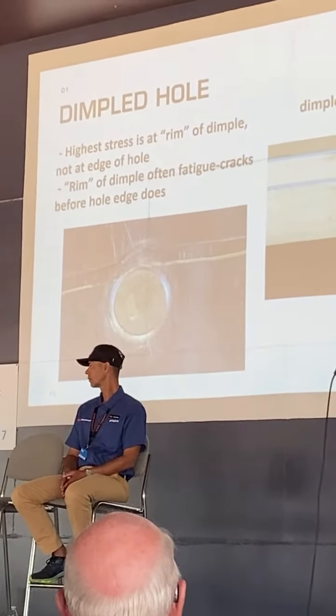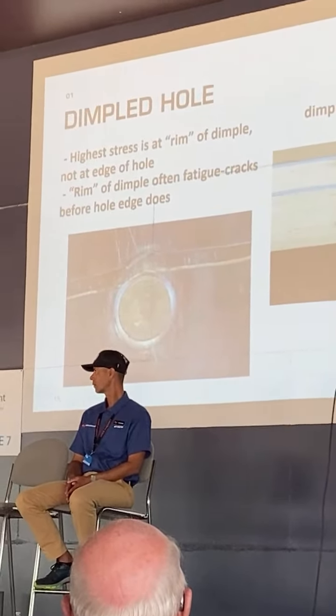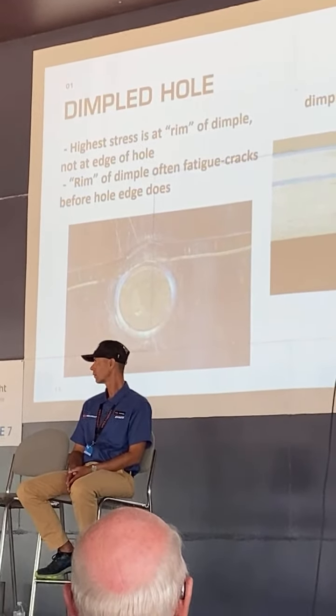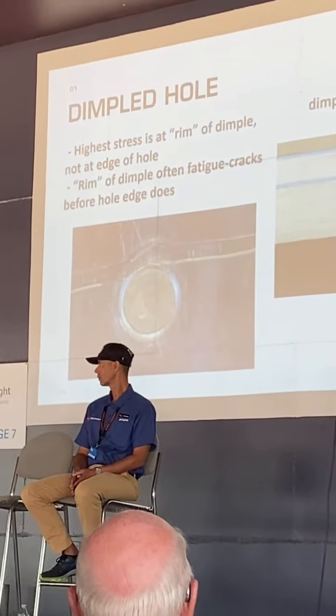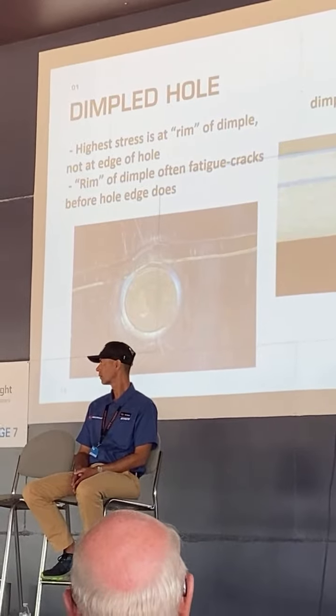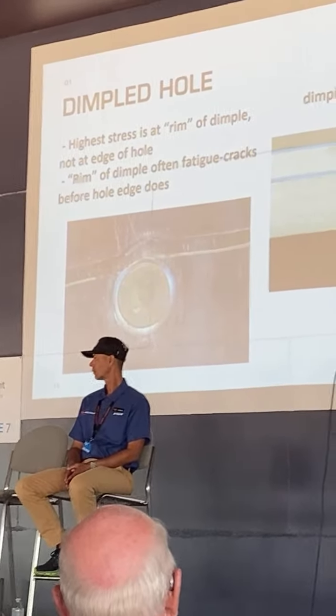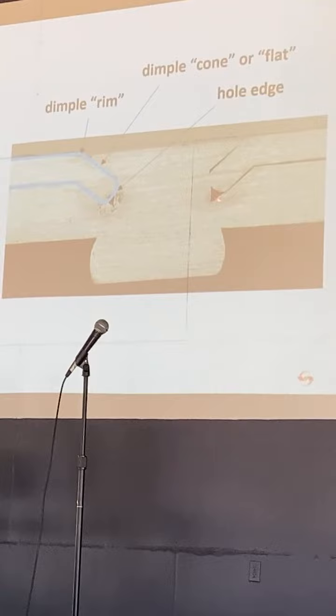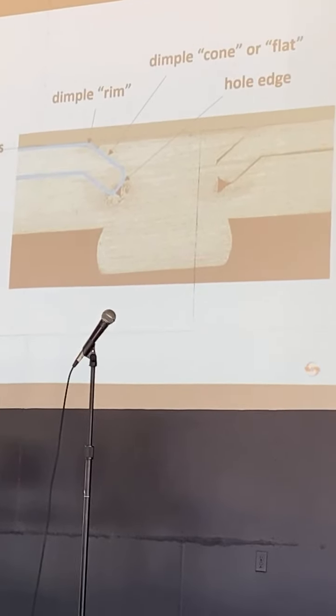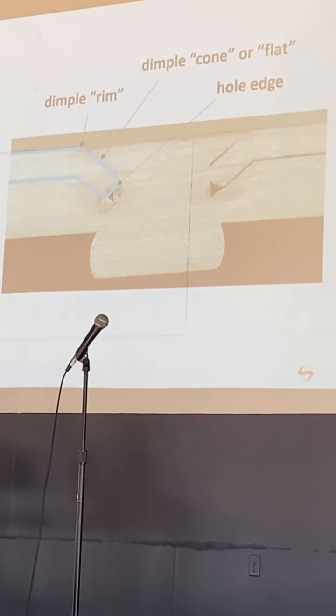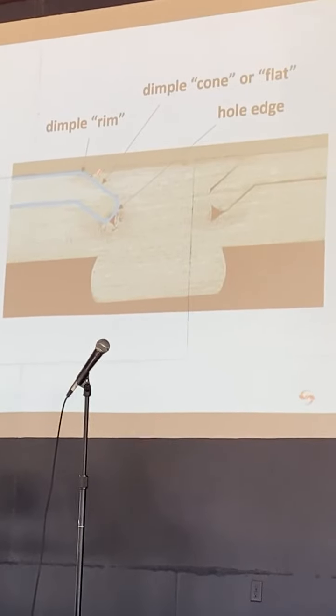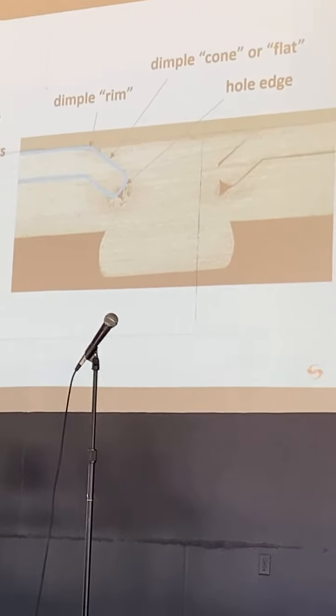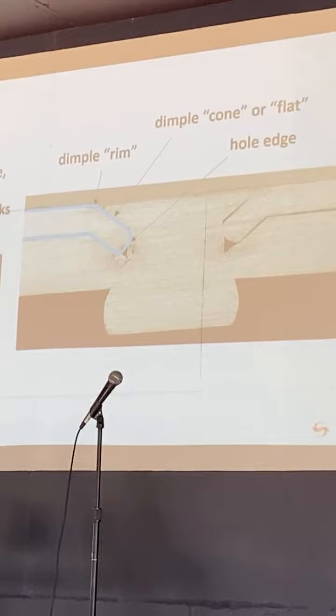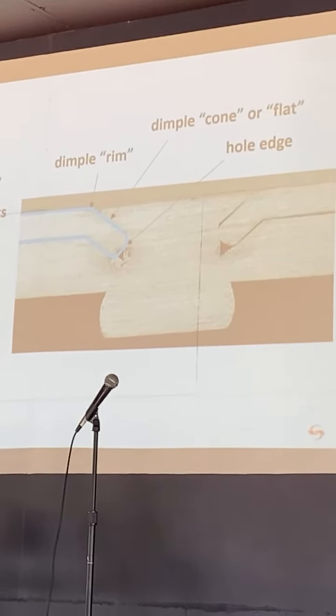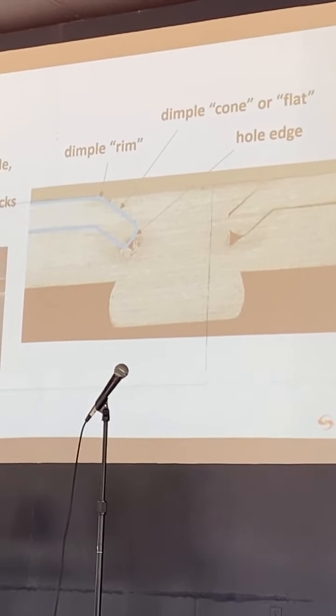So, defining more about a dimple, this is a little bit hard to see in definition, probably in the back. This is a dimple that we've cut apart so that you can see what the dimple looks like inside. You can see that the rivet doesn't fully fill this void. Here is the top sheet, as you can see in blue there. We have the dimple rim. I'm calling it the rim, defining terms here as we discuss this. This is the cone of the dimple, and this is the hole edge.